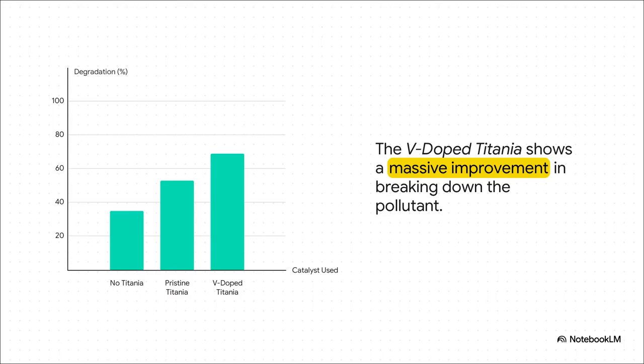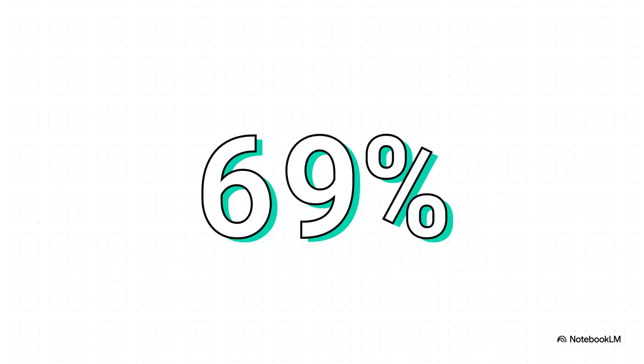With just the low-energy system alone, it broke down about 35% of the pollutant. Okay, add in the original, regular titania, and that number bumps up to 53%. Better, but the new vanadium-doped titania, a whopping 69% degradation. That is a huge improvement. 69%. That's the number. That number proves the whole concept.